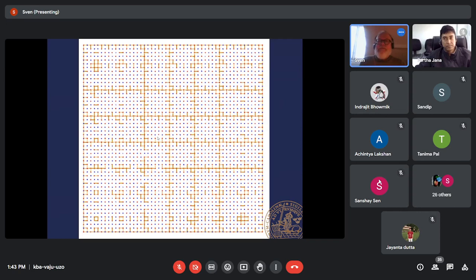So the rock salt structure is not stable because of the interactions between heteroatoms and homoatoms, so that the tin atoms want to be a little bit closer than they get to in the rock salt structure. And this means that you can only build the blocks here to a certain size, and then you get a layer of pure tin.